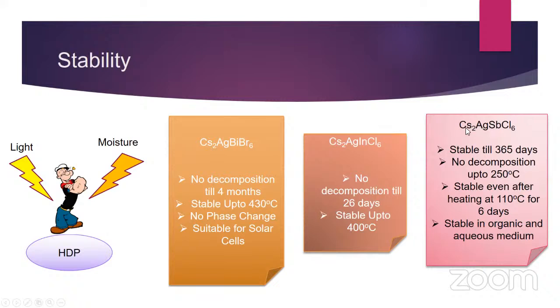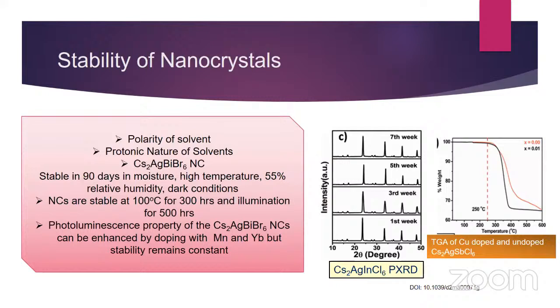And for the Cs2AgSbCl6, they are stable till 365 days, that is almost a year, and there is no decomposition up to 250 degrees centigrade, and they are stable even if you heat them at 110 degrees continuously for 6 days. And also they have shown great stability in organic and aqueous medium. And yes, here you can also see the nanocrystals, they are also very stable.